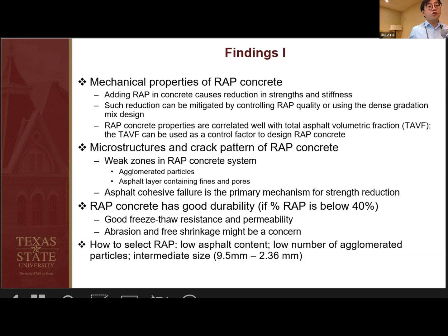We also did some microstructure analysis using an X-ray CT microscope, and we found the asphalt layer is a weakness point, so that most of the time the cracking passes through the asphalt layer. That also confirmed why we can control the strength by controlling the asphalt content. Durability, we did not find a lot of durability issues if you just use 40% RAP. And we also propose some methods that can help select the best RAP for concrete applications. So essentially, we just need to control the gradation.